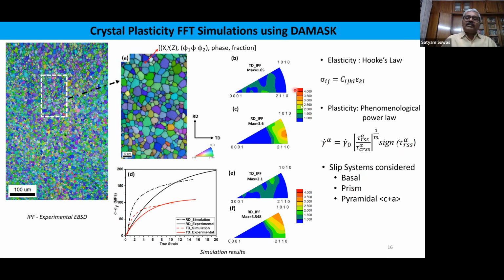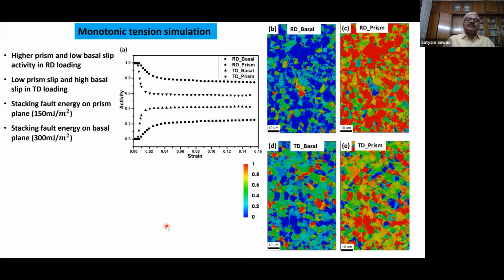And we calculated the inverse pole figure, and most importantly, the stress-strain curve was calculated here after deducting yield strength. And we could see the differences were almost in the same order, except for the fact that saturation has occurred much earlier with simulation, and a little bit of deviation from experiments could be seen at higher strains and lower strains, but the curve passes through this, so this much deviation is expected.